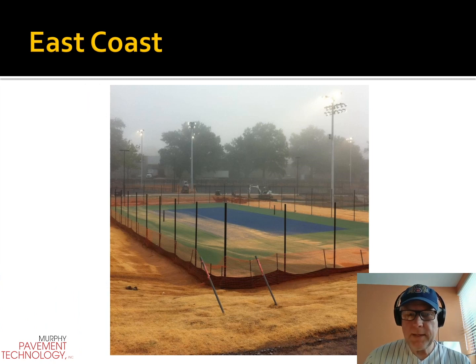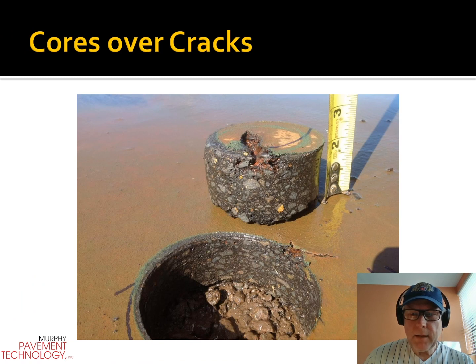Here's something from the East Coast where you know that moisture and debris, the grit, so to speak, of the embankment was getting onto the asphalt. And then cleaning it incredibly well before coating is going to be a very important task. Sometimes not always done perfect. And autopsy and forensic work, I should say, includes cutting cores over areas that began to crack and delaminate. And primarily it just became an issue where contaminants still existed.